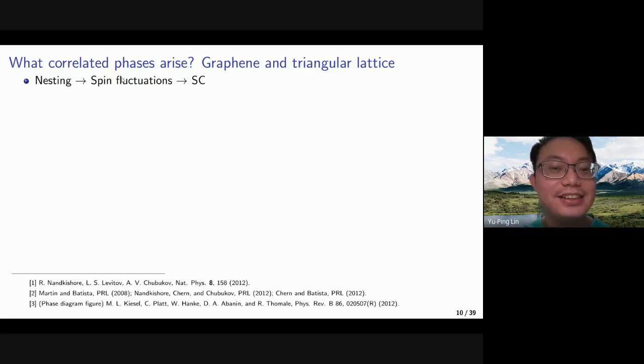Okay, thank you. Yeah, so this is what I mentioned just now. We want to know what are the correlated phases that are the leading instability. For graphene and the triangular lattice, we can think of it as a procedure like this. First, we have the nesting at the Van Hove singularity, and the nesting could lead to some one-loop leading divergence, which could trigger the spin fluctuations, which have finite momenta Q1, Q2, Q3. And if we go further to lower temperature, it will trigger superconductivity. The Cooper pairs may be mediated by some kind of antiferromagnetic spin fluctuation, because the spin fluctuation is at finite momenta.